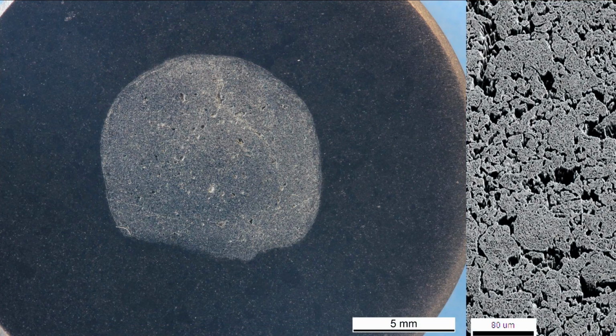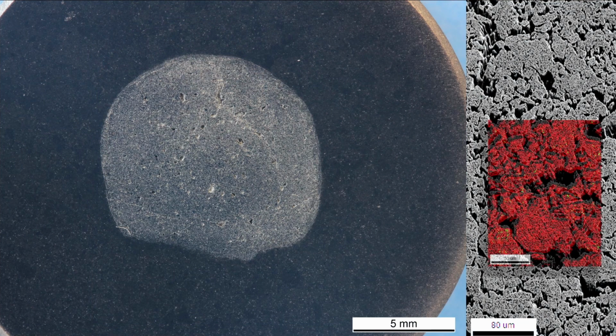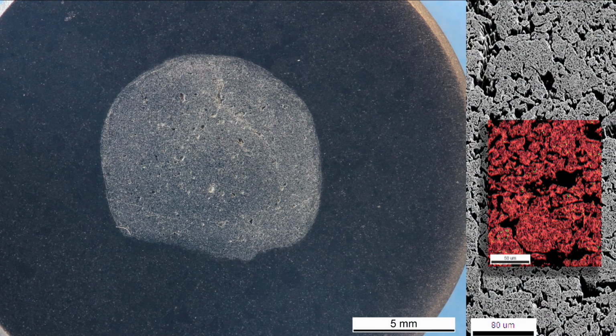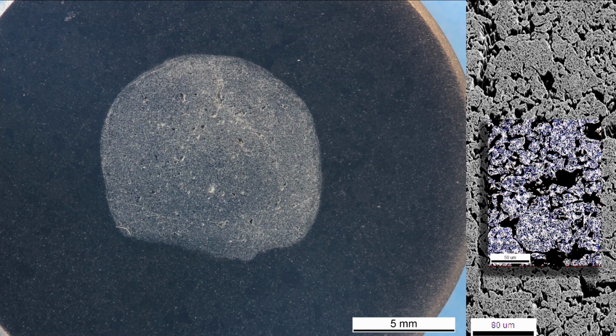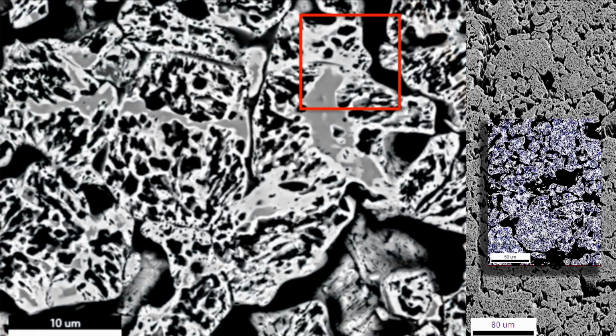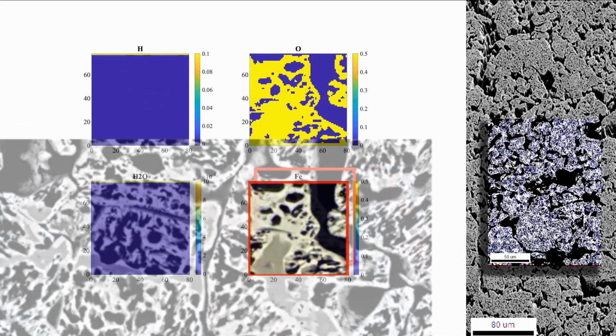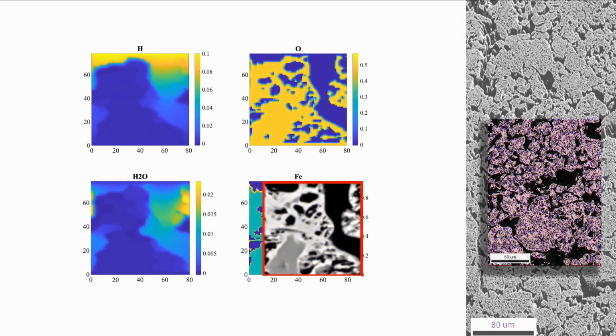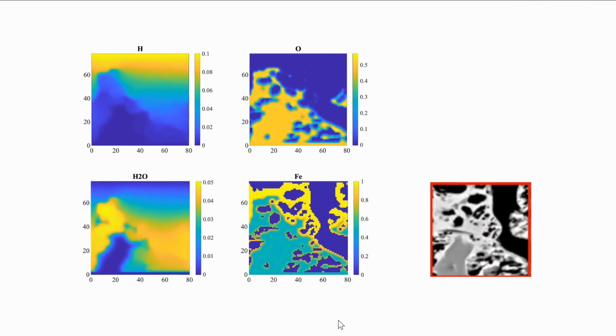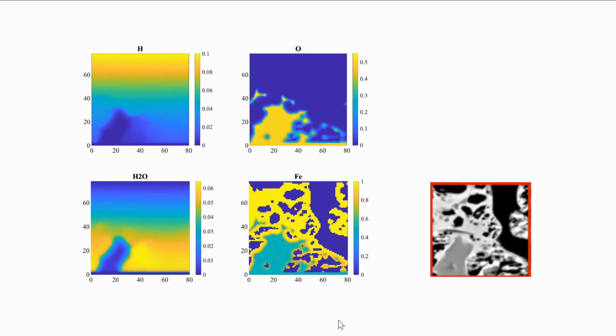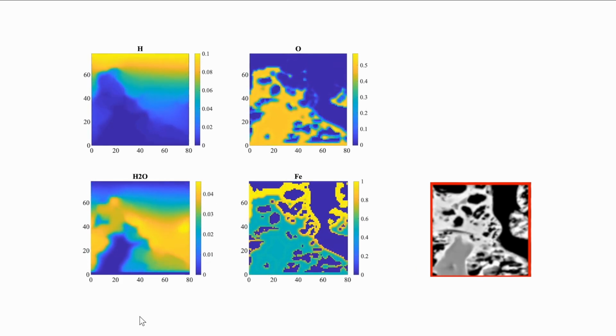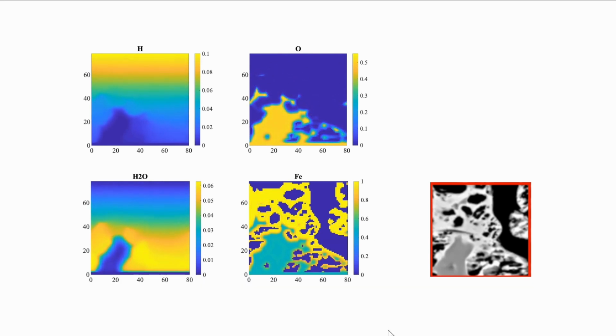When you cut it open, you can subject it to all kinds of microscopy mapping techniques, be it chemical or structural. You can look at the phases, at the distribution of the grain boundaries, and so on. So the same things that you would do in ordinary materials, and then you get these very complex microstructures revealed. Now we are also interested in subjecting them to a boundary condition treatment through a corresponding phase field calculation. In this phase field calculation you can see the diffusion of the hydrogen, of the oxygen, and you can see the formation of the water as a reaction product. In this diagram you see how the iron is starting to penetrate the former oxide.